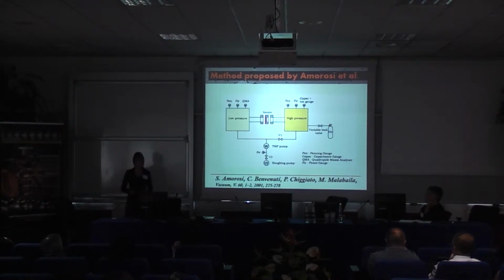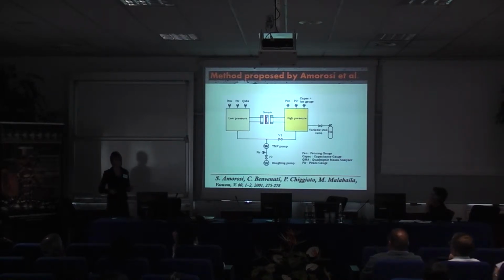Probably the best known method for evaluation of porosity inside niobium films was proposed by Amorosi, Benvenuti and collaborators. The idea is in measurement of the conductance of the gas through the film.